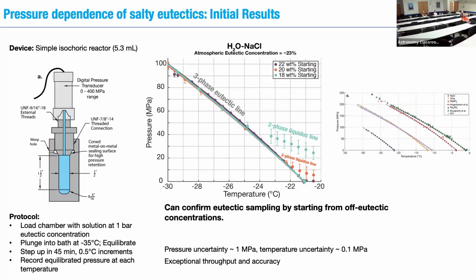But when you hit the eutectic composition, where you have 3 phases simultaneously present, ice, the liquid, and then the solute-bearing solid phase, you only have one thermodynamic degree of freedom. So at any given temperature, there are no options for your pressure or your concentration. Everything must converge to the same line. And you can see here that it does. Because when we start at these lower concentrations, as it's freezing in the 2-phase region, you get solute rejection that ripens the remaining solution to the eutectic concentration at that pressure, and then everything converges onto the same eutectic line.